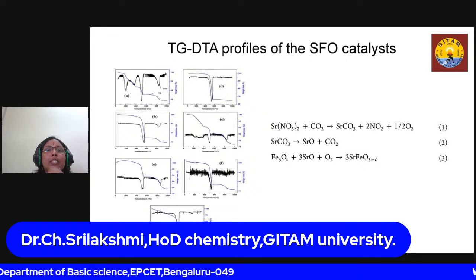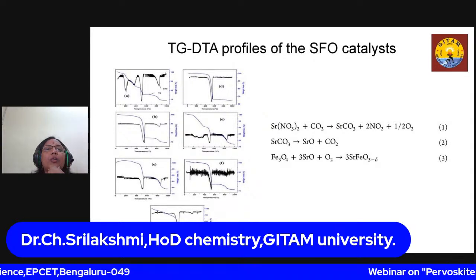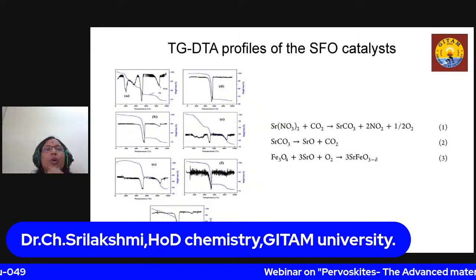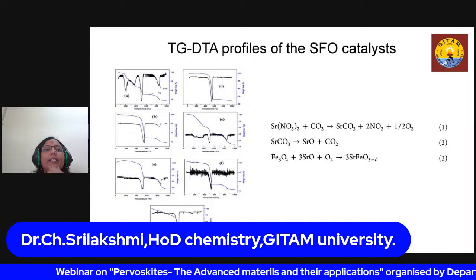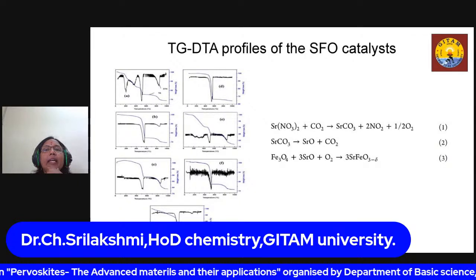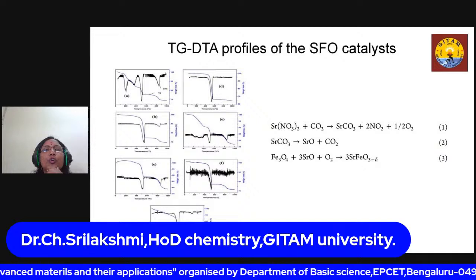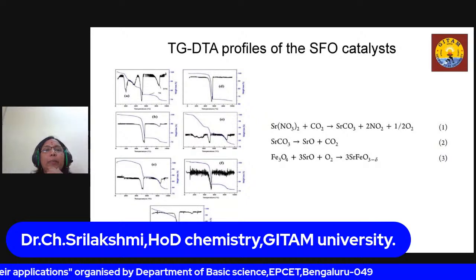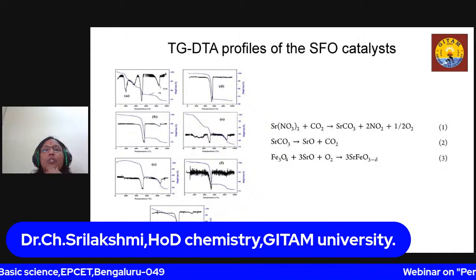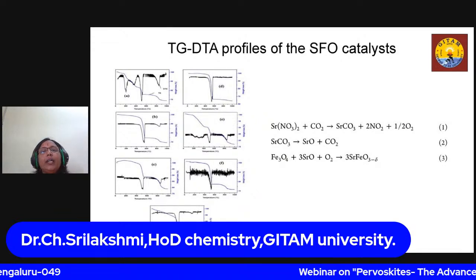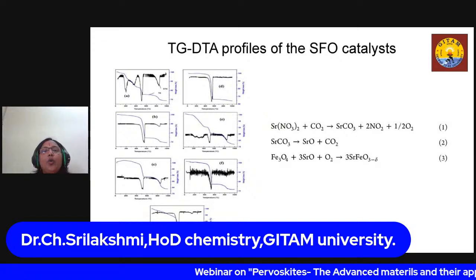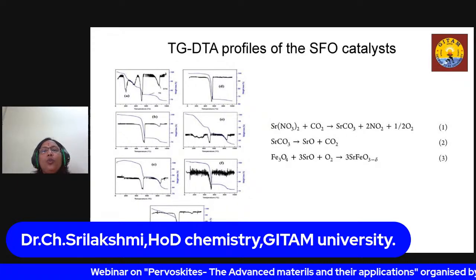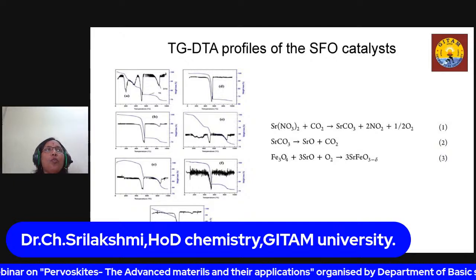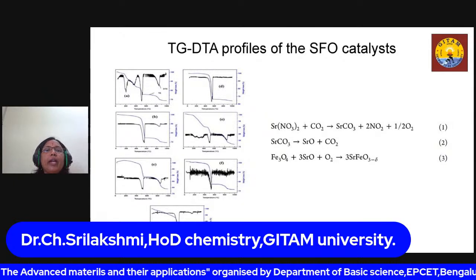So this shows that there are four major weight losses. First is the loss of water, and second, an endothermic peak, is decomposition of organics. Third is strontium nitrate interacting with CO2 and converting into strontium carbonate. This is the peak, very important, at around 850. So strontium carbonate decomposes into strontium oxide, and further interaction with the iron oxide in the presence of O2 gives rise to the formation of the desired compound, which is a defective strontium ferrite structure.